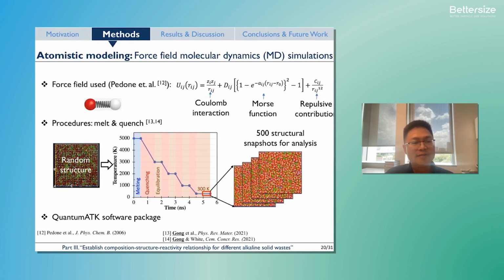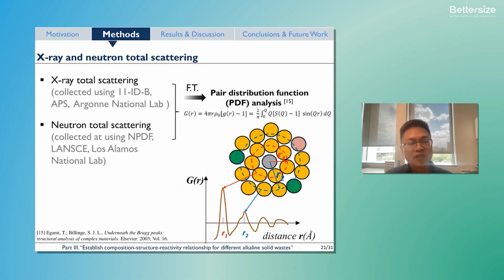To generate the detailed atomic structure of these amorphous materials, I used molecular dynamics simulation following a simulated melting and quenching process as illustrated in this figure. You can find more details in the publication if you are interested. In the interest of time, I won't get into details. To verify whether the structures we generated using this computational method are reasonable or not, we have collected some X-ray and neutron total scattering data, which can be directly compared with our simulation data.